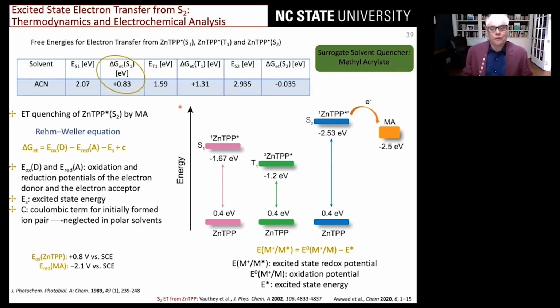But just to show you, if we do electron transfer from the singlet or the triplet, they're both uphill. Obviously, you can see that. They won't happen. But from S2, it's downhill. It's the only downhill process. And I can tell you now, every single control experiment has shown S2 is the only way to get this to polymerize.